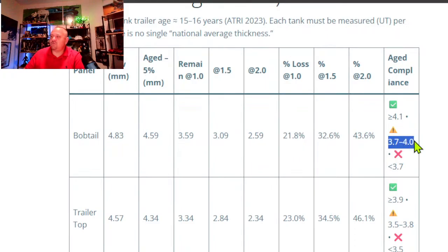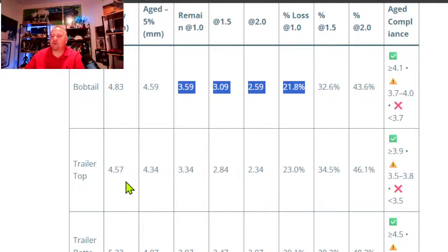If you are 3.7 to 4.0 millimeters thick, then you have to pay attention to it and it must be inspected thoroughly. Anything under 3.7 millimeters thick is out of compliance, and that's it. As soon as you remove 1 millimeter on an average 15 to 16 year old tanker, according to data, you're already underneath the threshold of 3.7 millimeters. You're at 3.59. So there's no reason to even look at the possibility of sanding anything with that.